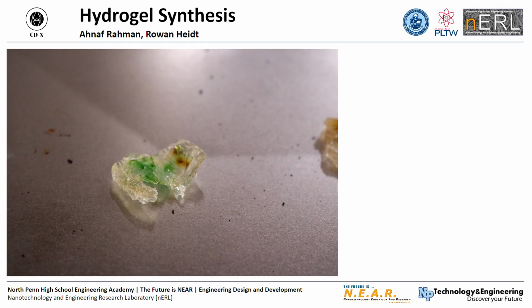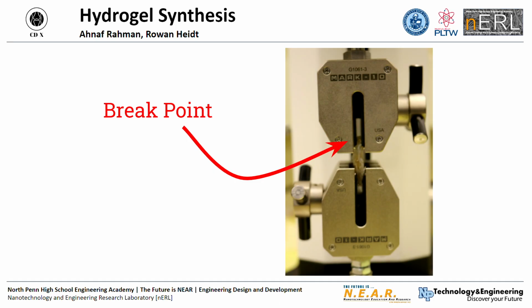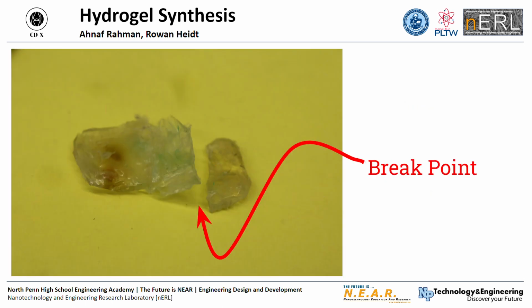When we pulled it out of the solution, we did notice there was a slight issue. One of our pieces had a significant weak point that would later hinder our tests. As can be seen here, the sample's weak point got caught in the top clamp of the tensile tester, which pulled it clean and had a clean break point along that weak point.